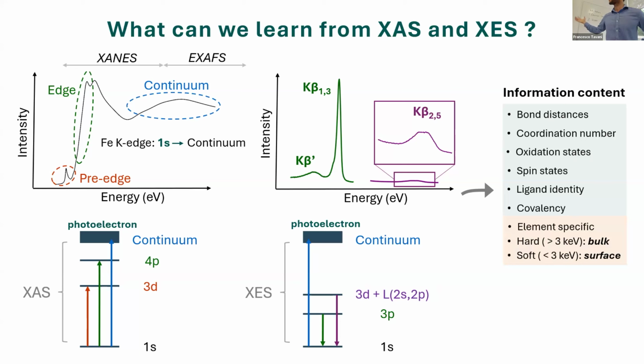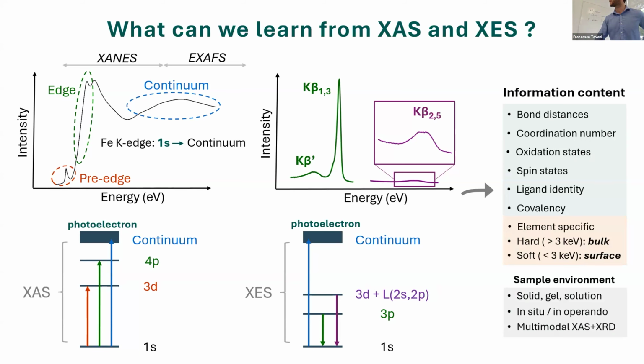These techniques are element specific, which is nice. We can probe the bulk if we use hard X-rays, due to the higher penetration depth of the more energetic X-rays. We can also probe the surface, which is also quite interesting, if we use less energetic X-rays, since they penetrate less into the material, and these are often referred to as soft X-rays. I will tell you a little bit more about this in the next slides. And another important part of this is that the sample environment is quite vast.